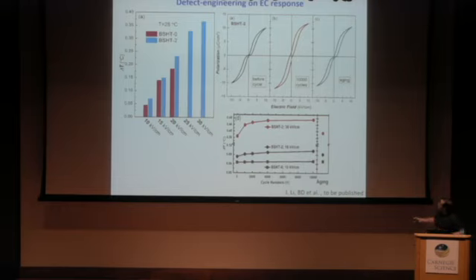And what we did also here, we cycled many, many times, because we know by cycling we can move also the defect. We have to take into account the mobility of this defect. And you see that when we start at the beginning, it's like this. After 10,000 cycles, it changed a little bit in the sense that it starts to have polarization. It looks more ferroelectric than pinched. But if we remove the electric field and leave it during 24 hours, we recover exactly the same state as the beginning. So you can think also to design a kind of device by playing with these pinched hysteresis loops, and of course cycling and aging in the system.